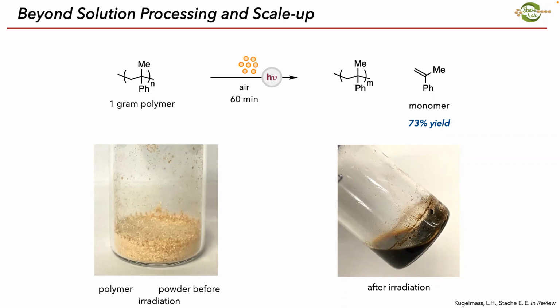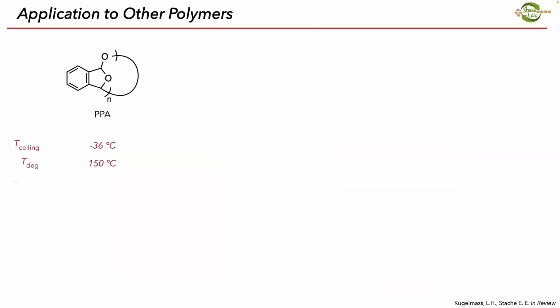It depolymerizes in an even higher yield as we scale this up, 73%, with the rest of it being the leftover polymer. And we can do this in a distillation type setup where the monomer comes over into a receiving flask in pure, analytically pure form. The NMR looks beautiful, very clean.